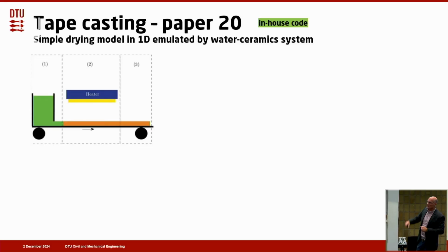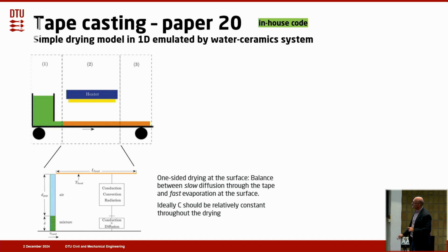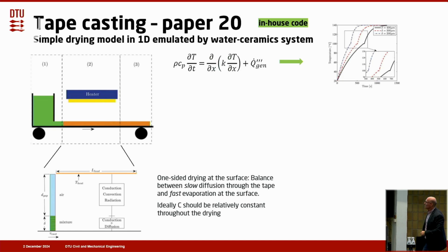So if you see here, the drying you have here with the blue heater, and the point is that it's one-sided drying at the surface. So it's a balance between the slow diffusion through the tape and the fast evaporation at the surface. And ideally, you would like to get a more or less constant concentration throughout the tape, and this is, of course, not possible. But you would like to at least get there to some extent.